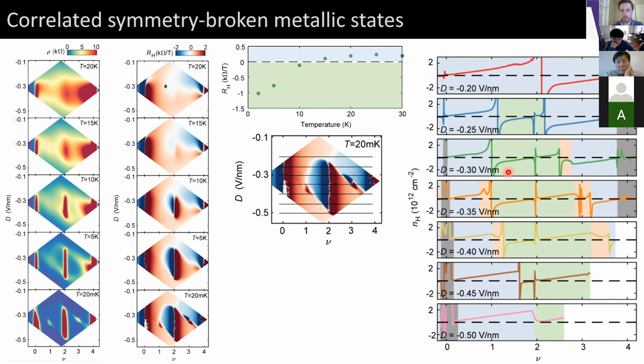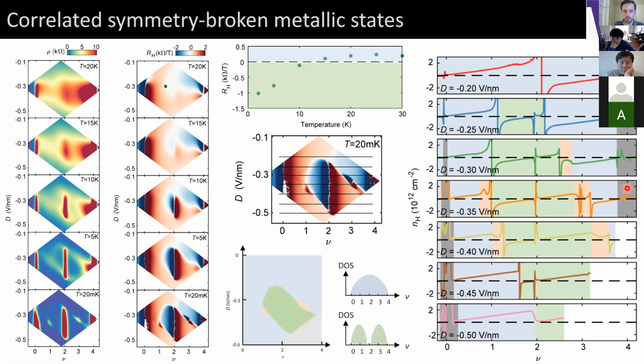So those seem to indicate that a single degeneracy is lifted upon the formation of each of these correlated insulating states. So the green regions correspond to twofold degeneracy, and the orange region corresponds to no remaining degeneracy. And so I can just construct these things into a phase diagram, which should mimic what this is doing, where I'm just coloring based on whether the sign of the Hall coefficient is what we expect or opposite of what we expect.